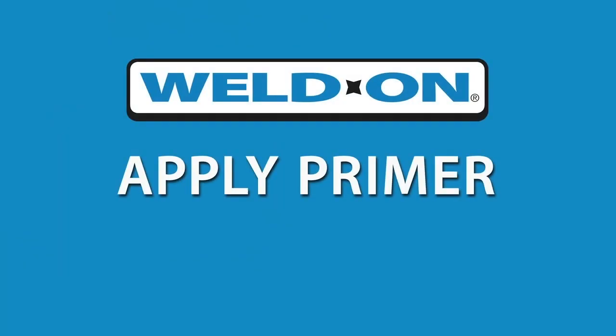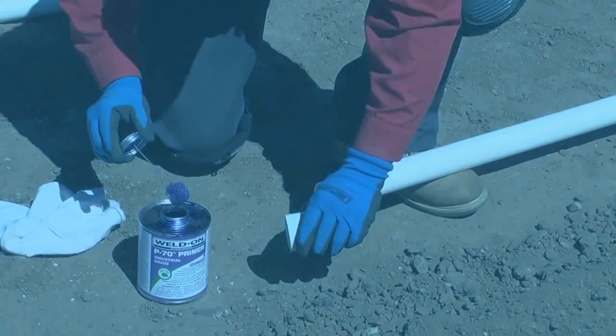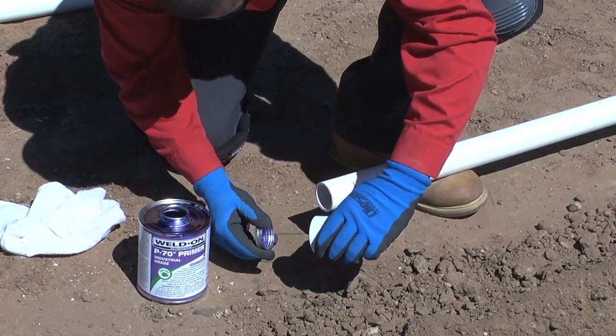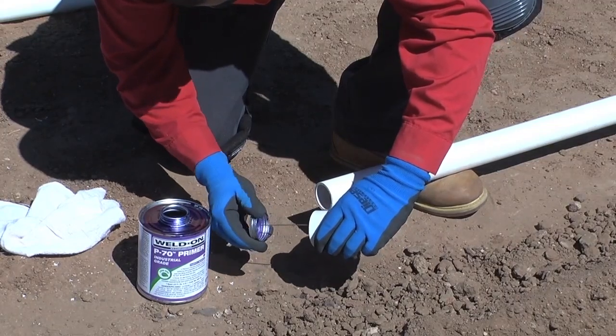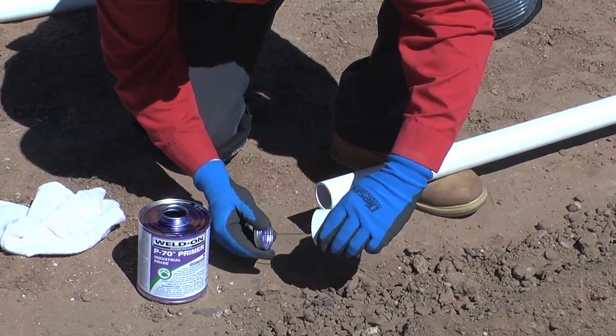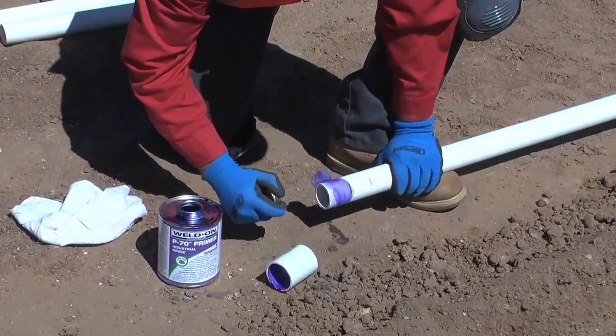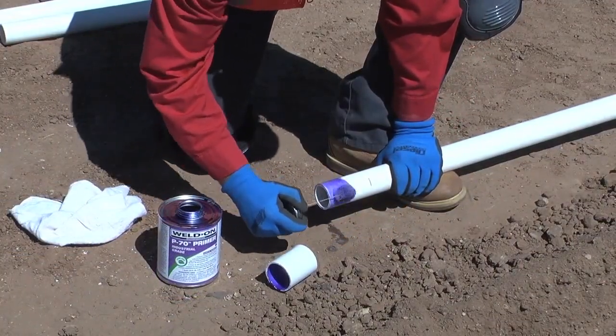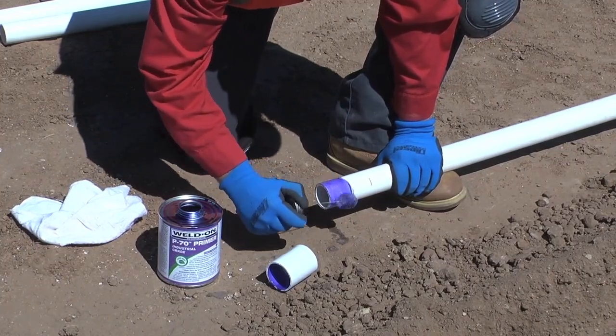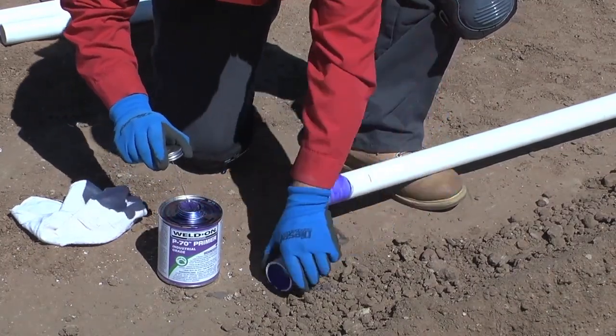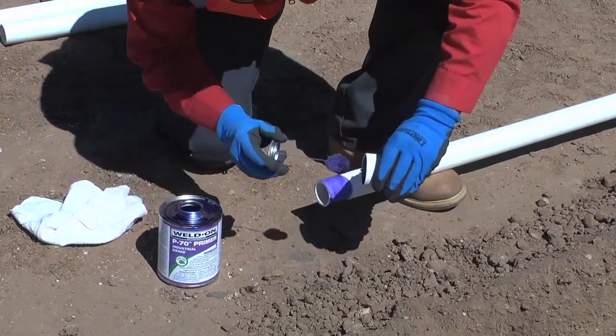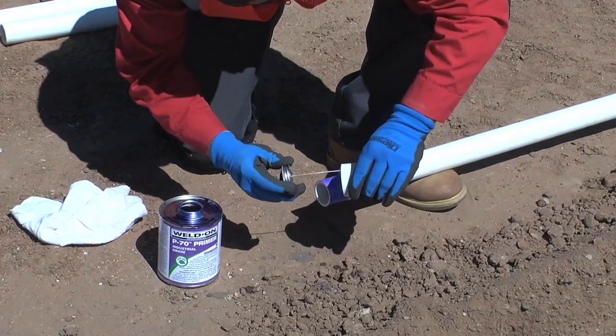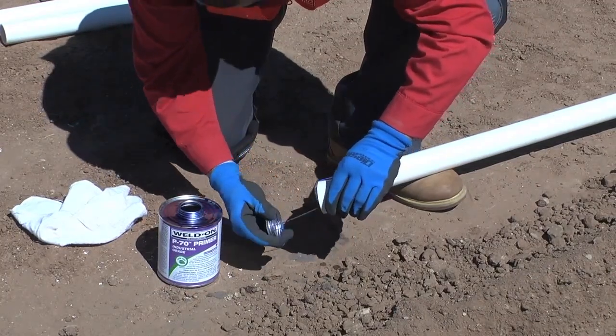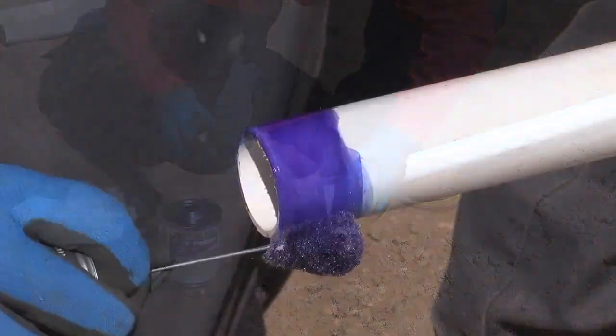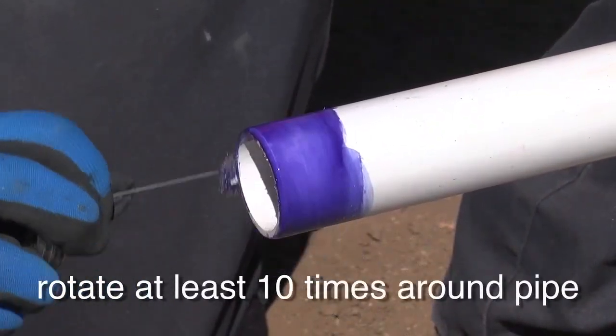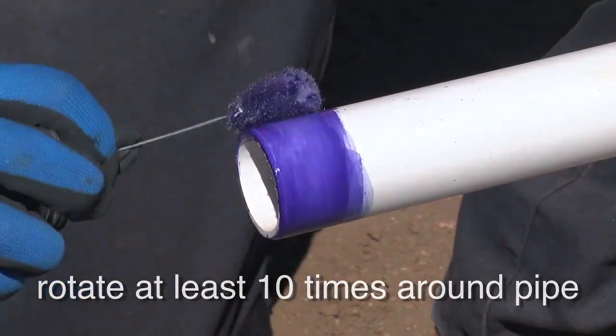Now apply primer. Tilt the fitting socket downward, vigorously working the primer into the fitting socket. Keep the surface and applicator wet until the surface has been softened. Remove any puddles. In the same manner, vigorously apply the primer to the end of the pipe, equal to the depth of the fitting socket. Then apply a second application of primer to the fitting socket. Do not allow primer to run down the inside of the fitting or pipe. In the case of belled end pipe, do not allow the primer to run past the bell socket into the pipe. For each application, rotate the applicator at least 10 times to ensure proper primer coating.